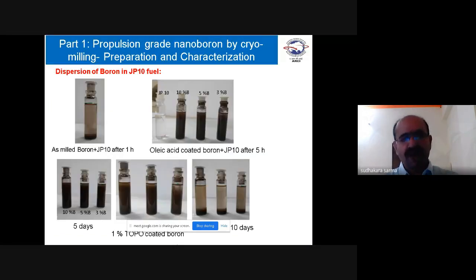And the final objective is to make a slurry fuel for the missile. For that, we mixed the boron powder into the JP10 fuel without coating. You can see the first image. Without coating, if we add the boron, it is settling down within half an hour.